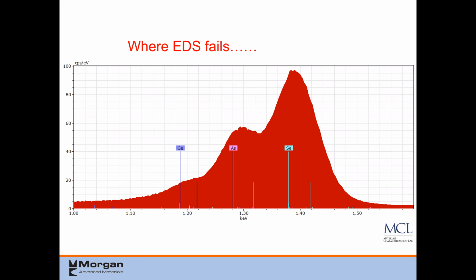So EDS is a great technique for your qualitative analysis, or just giving you a rough estimate of what the composition is. But if you really want to get into the composition, you have to worry about overlaps and things like that. This is an example of work that I did at Penn State. They were trying to use EDS to determine the ratio between germanium, arsenic, and selenium in a glass that they made. And as you can see, the 3 different elements overlap very strongly in EDS. To analyze an EDS spectrum, you fit a Gaussian to the peaks. Well, if you look at this, where are you going to fit that Gaussian exactly? What kind of tail do you have for the arsenic, or what kind of tail do you have for the germanium?